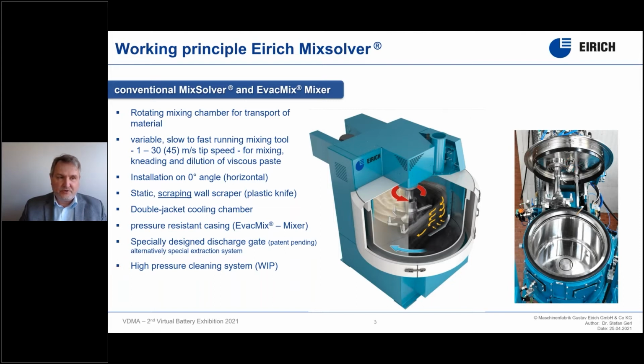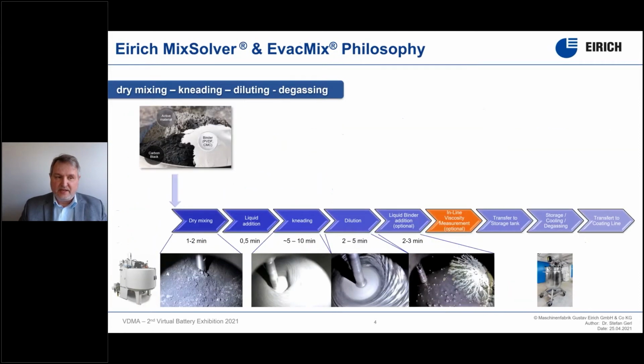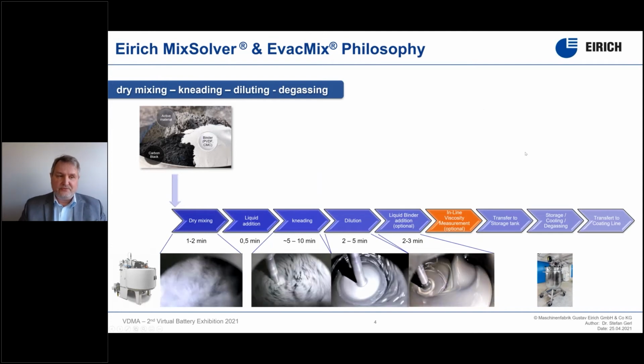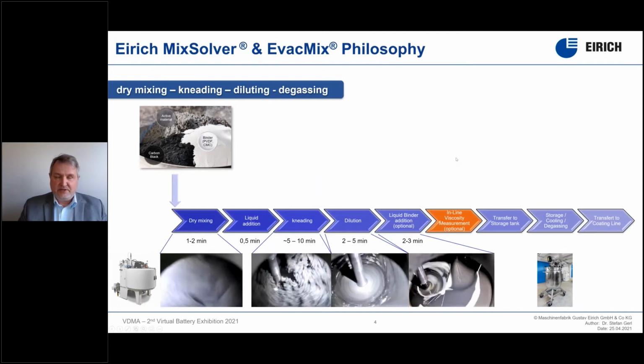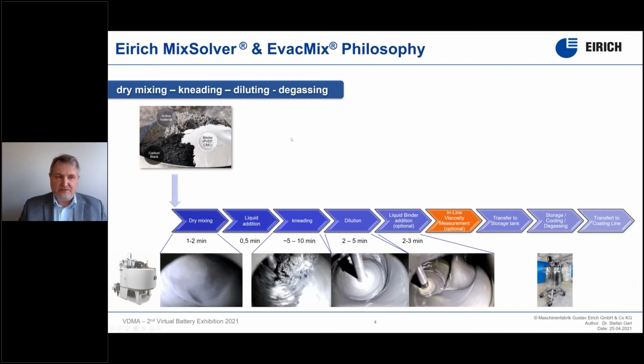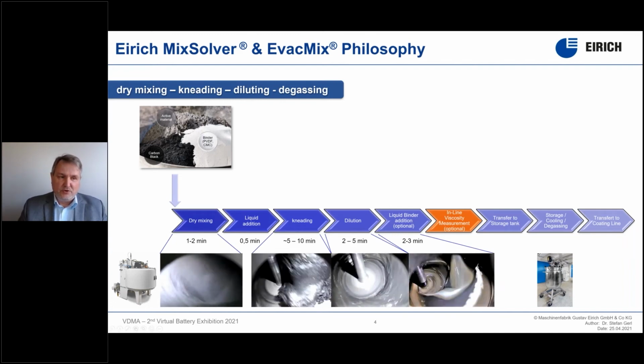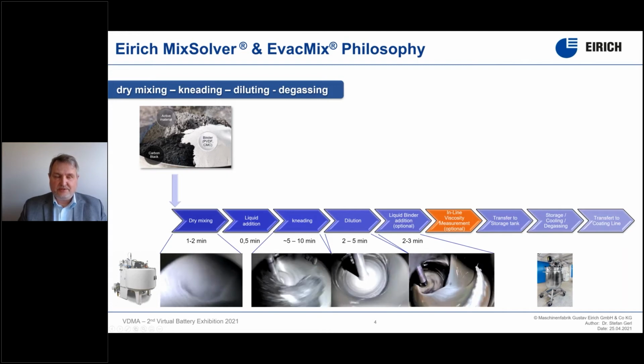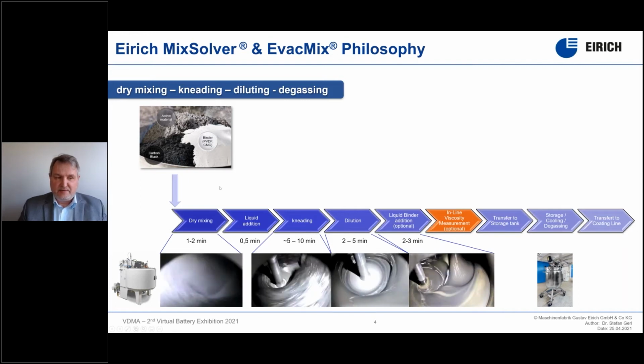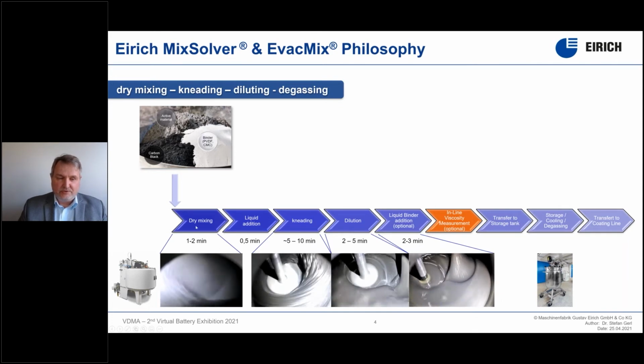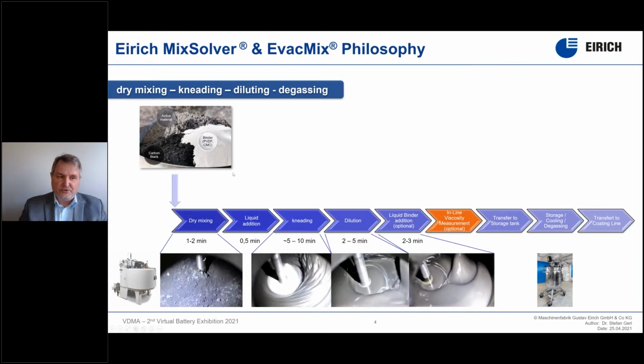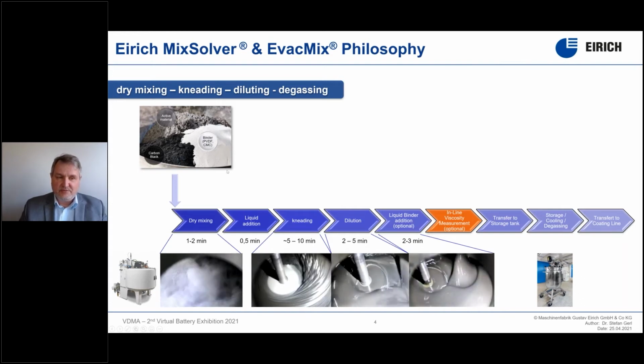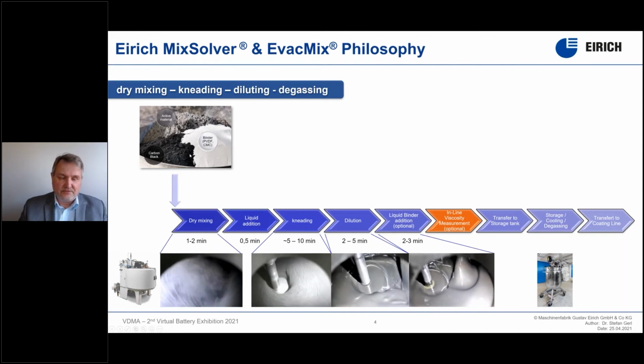How does the process work inside of the EIRICH mixer? We follow a certain philosophy that our mixer is capable of running through any consistency. So we promote adding all dry raw materials. This includes the active material, of course, a conductive carbon, as well as a binder. We start with a first intensive dry mixing process, which usually takes 1 to maximum 2 minutes. Firstly, to separate the binder particles from each other, to put in the active material and the conductive carbon in between, and to disperse the conductive carbon already.